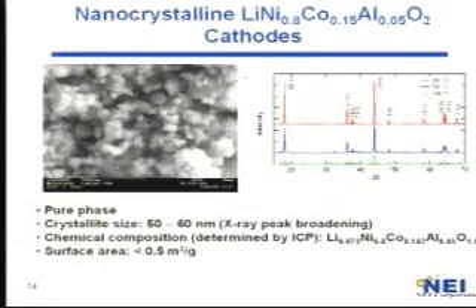But as you can see from a FESEM micrograph, it's a highly aggregated material. The surface area of this material is less than 0.5 meters squared per gram. But the crystallite size, the domains, what we call, is in the range of 50 to 60 nanometers. And then we compare this material with the existing material with the same composition, which is a coarse material where the surface area is around 1 meter squared per gram, but the crystallite size is almost 500 nanometers. So they're much larger than this material.